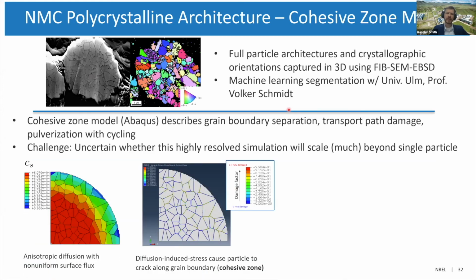So we have integrated this into an Abaqus cohesive zone model. It considers the anisotropic diffusion in each of these different grain directions. We have done a lot of work to have boundary conditions on the outside that represent Butler-Volmer conditions, as opposed to assuming uniform flux on the outside, because there's going to be preferential grains which have higher flux compared to other grains in the system.